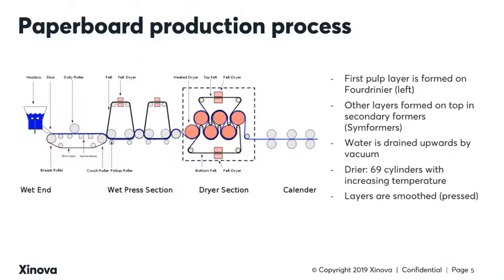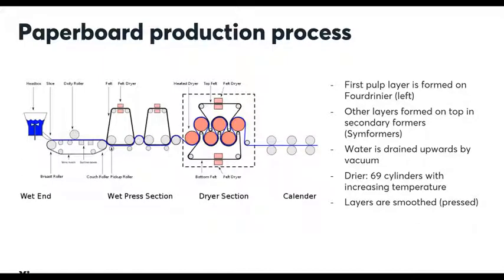The first pulp layer is formed on what's called a Fourdrinier. You can see a schematic on the screen. This process includes pressing the wet pulp using many rollers, a dryer section where 69 cylinders with increasing temperature efficiently dry the pulp, and the water is drained upwards by vacuum. This is followed by a calender section where 2 or more rolls make the paper surface extra smooth and glossy. Other pulp layers are then formed on top in secondary formers called Symformers.